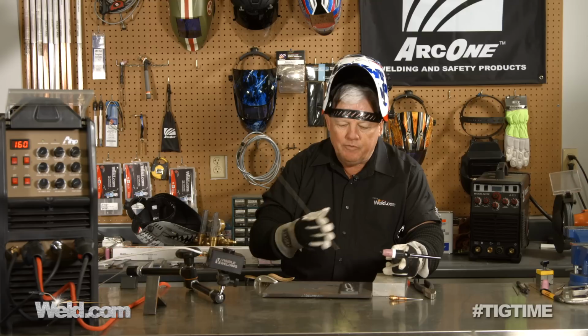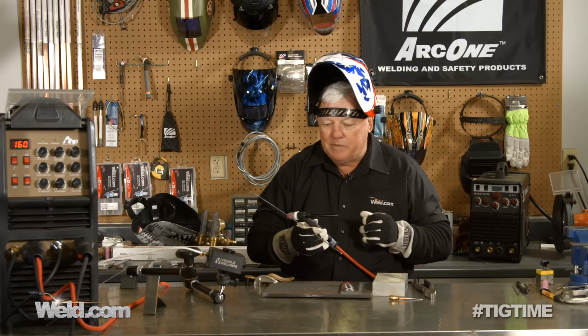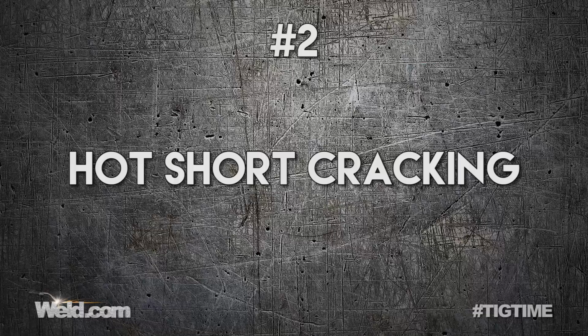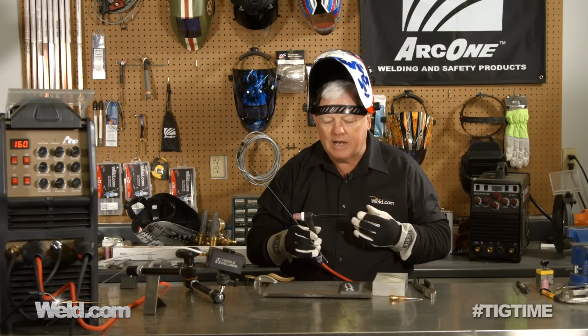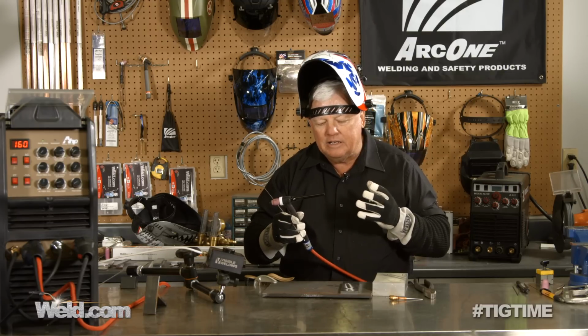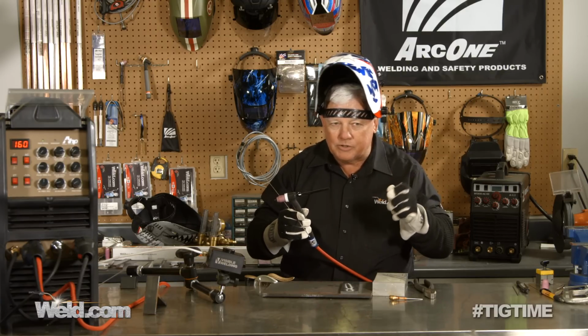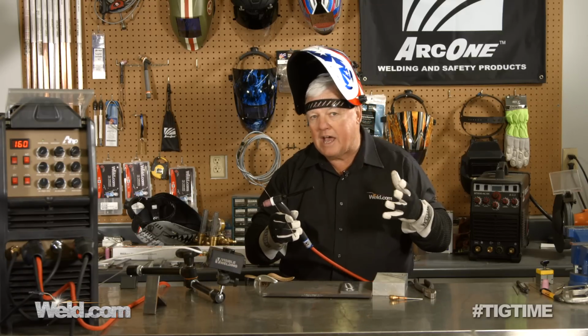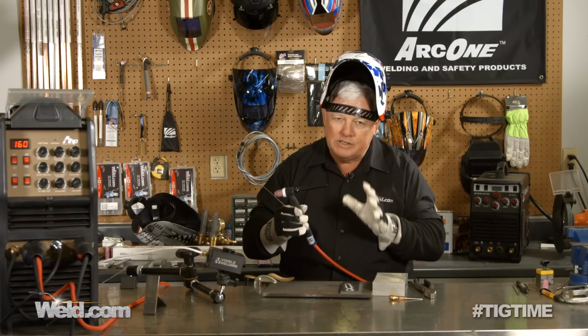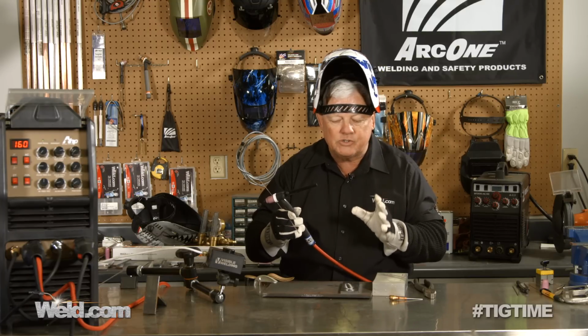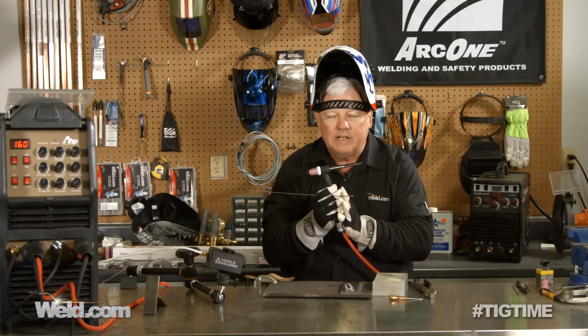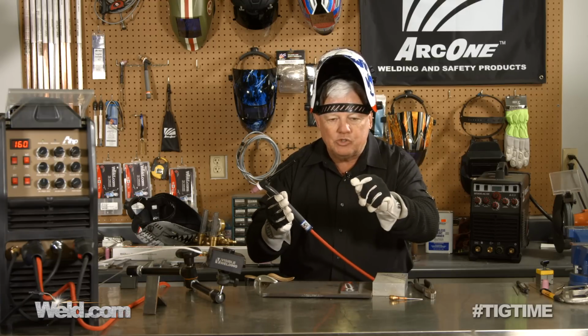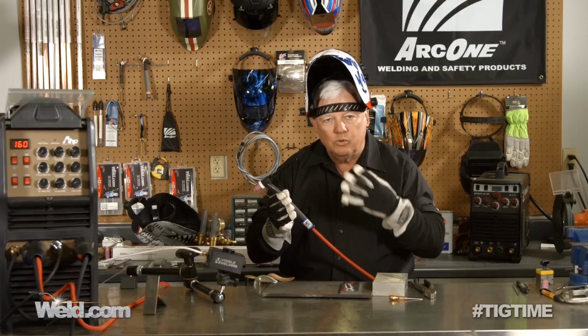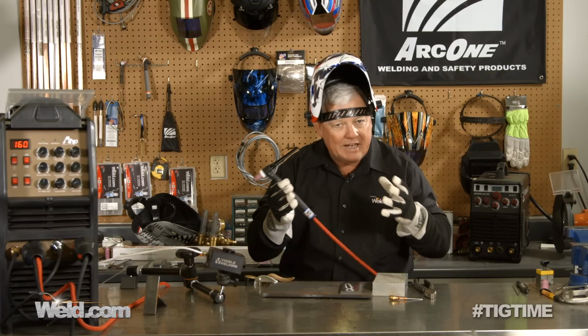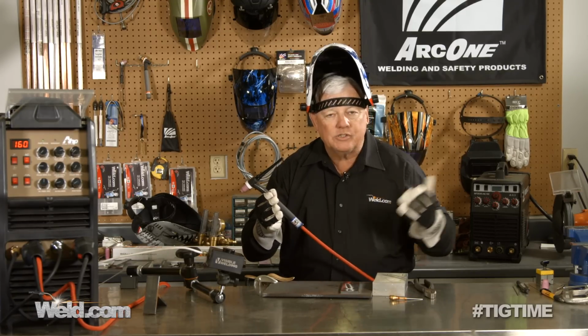So I'm going to move on to the next mistake that's made by most people, and a lot of it has to do with something called hot short cracking. You can weld steel and stainless steel and other materials, and you can fuse it, and you can even fuse the tacks. In aluminum welding, it's sensitive. Hot short cracking is when aluminum transfers heat so fast that you have a liquid puddle, and as soon as it cools off and transforms back into a solid, it tries to crack right down the center of your weld.